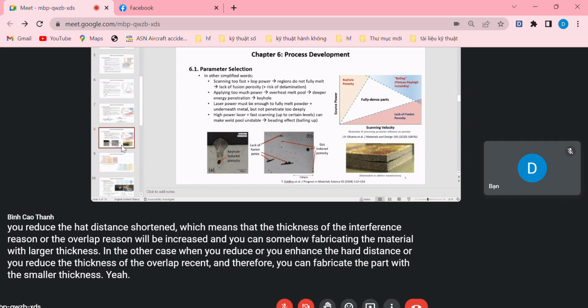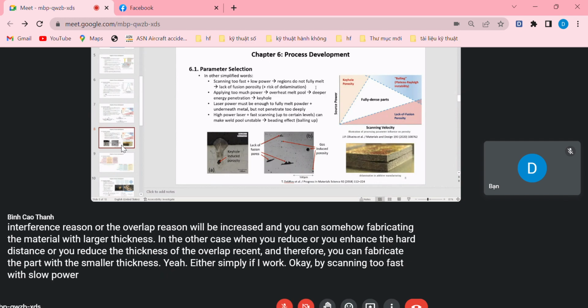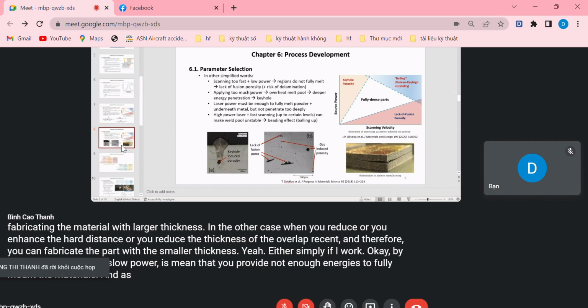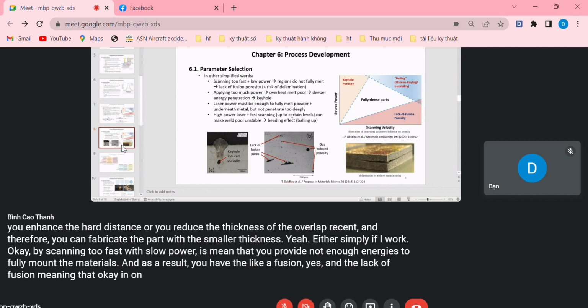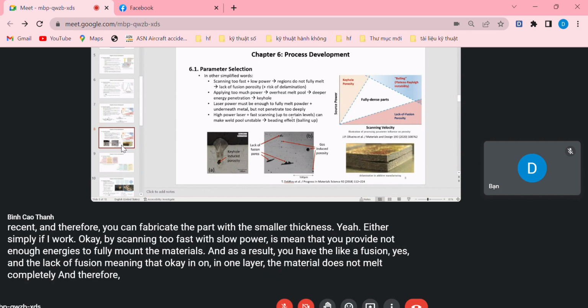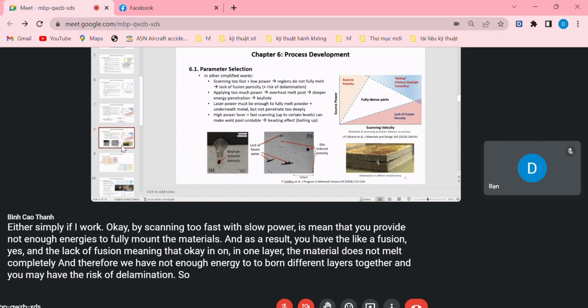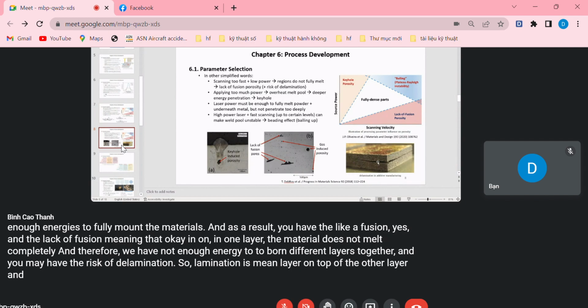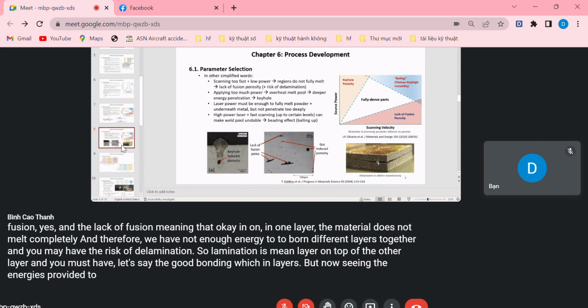In other simplified words, by scanning too fast with low power, you provide not enough energy to fully melt the materials, and as a result you have lack of fusion. Lack of fusion means that in one layer, the material does not melt completely, and therefore we do not have enough energy to bond different layers together, and you may have the risk of delamination. Delamination means layer on top of another layer, and you must have good bonding between layers, but since the energy provided to wet the layer is not enough, you have the risk of delamination.